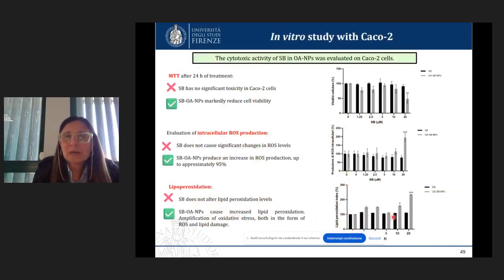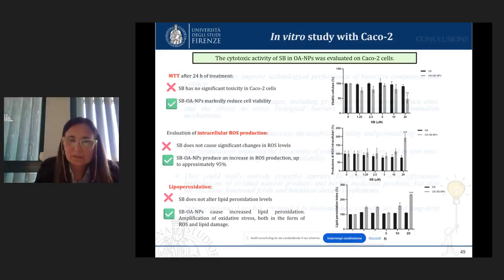These nanoparticles were studied for their anti-cancer activity, and the cytotoxic activity of silibinin loaded in oleanolic acid nanoparticles was considered on CACO2 cells. In this case, CACO2 cells are considered our cancer cells. From preliminary results, we obtained that silibinin-loaded nanoparticles reduce cell viability and show cytotoxic activity with respect to silibinin alone, increase the ROS production, and also increase the lipid peroxidation. Then, a good result for silibinin when the molecule is encapsulated inside the nanoparticles.